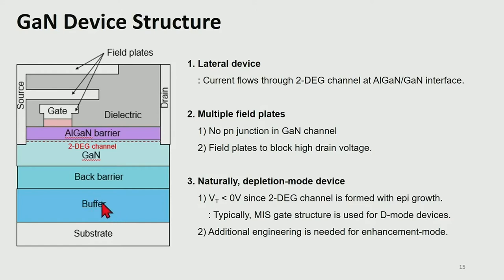There are a couple of reasons for that. First, the high electron mobility channel is formed automatically during the epi growth, so there is no need to form an additional doped layer for electron supply. And also, even though you want to do additional doping with the implantation, it's quite challenging to activate the dopants and cure the implantation damage. It requires about 1200 to 1300 degrees C annealing temperature, which can affect the overall epi quality and also other process conditions.